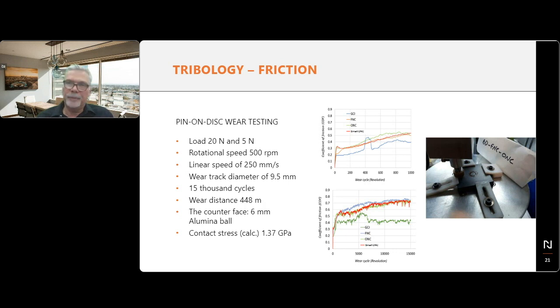So the way that nitrocarburized discs would really react at temperature, they will really warm up or heat up, sometimes become even red, will perform differently and will perform differently depending on the type of mating pads. So since the elimination of asbestos, what you see now is NAO, non-asbestos organic pads, which are kind of common in North America. They don't really perform extremely well at very high temperatures. So depending on the country and driving habits and even use of vehicle, you'll see semi-metallic or ceramic pads.